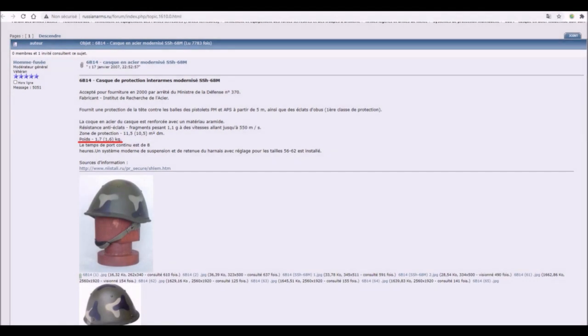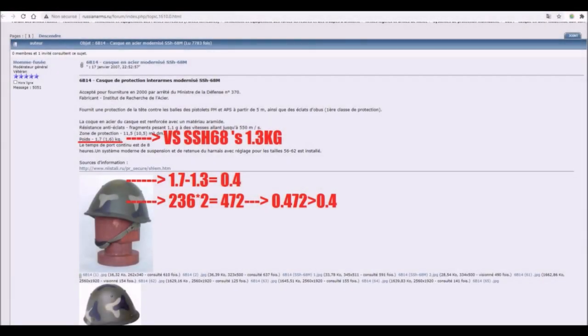So now, let's take into account the fact that a 6B14 has a weight between 1.7 kilograms and 1.9 kilograms according to most sources. We know a basic SSh-68 has a weight of around 1.3 kilograms. Let's add the weight of our theoretical composite liner, which is 472 grams. It gives us a total of 1,772 grams, which is very close to the middle between the lowest and the highest values of weight for the 6B14. This makes me think that the value given by Kalashnikov magazine of around 15 layers and the density I think is most likely, 150 grams per square meter, are both true, because the result we got from the calculation based on those two assumptions is very spot on with the weight that most sources give us regarding the 6B14.